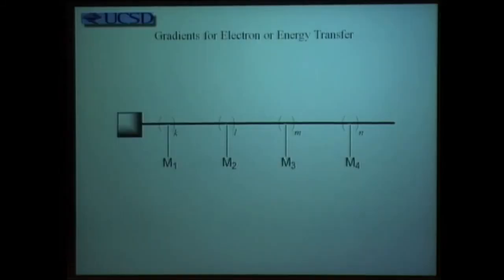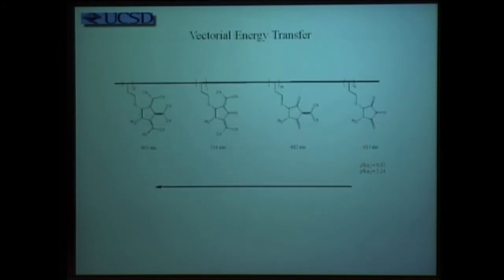Now, not only do we know that there's an interaction between these materials to generate complex semiconductors, but you could actually tailor a molecule by ranking of the oxidation potential, so that it goes from highest to lowest or lowest to highest. You can also use it by looking at a series of absorptive materials. So think, for example, if you had a series of materials, these are called croconic acids. Notice the one at the right has five such oxygen atoms. One of them is replaced by a maleimide derivative, once here, twice here, three times here.